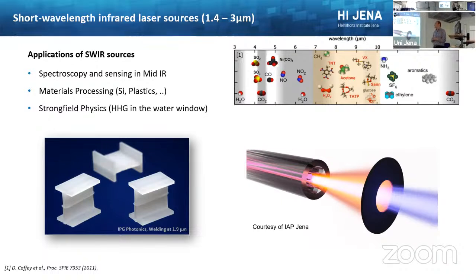It's also possible here for certain materials for processing. You can see there's a picture from IPG Photonics there. And especially in our group, we use this for strong field physics. We often use these laser systems as drivers for so-called high harmonic generation, where we basically convert this light from normally 1 micrometer down to wavelengths of just a few nanometers, the soft X-ray regime. If you want to go to very short wavelengths in the so-called water window, you need to start with longer wavelengths. It's difficult to get there from just 1 micron. It's easier if you start from a higher wavelength. That's why systems operating in this wavelength regime are very important to work on.